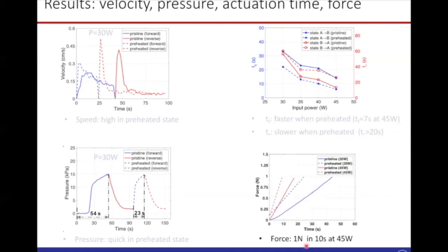And it can generate 1 Newton force. We show the force generated by the actuator at different input power. With the 45 watt input power, it could generate up to 1 Newton force in less than 10 seconds. So generally speaking, it can produce large transformation in limited time, and it can generate the sufficient pressure required for the transformation in limited time.